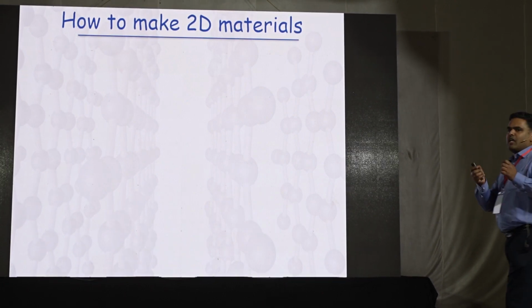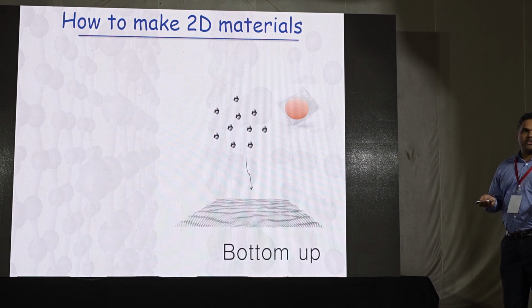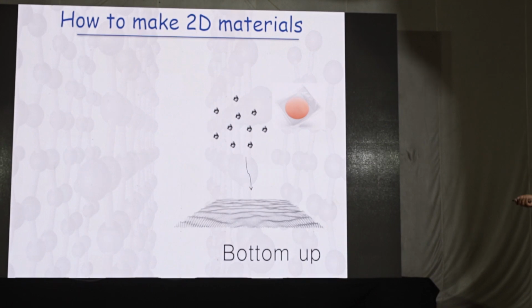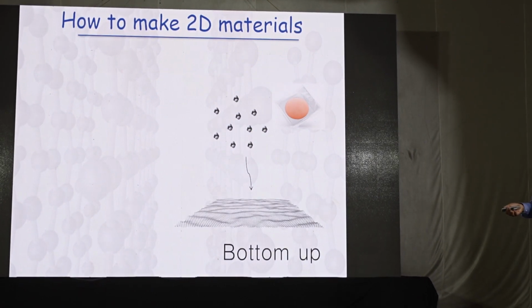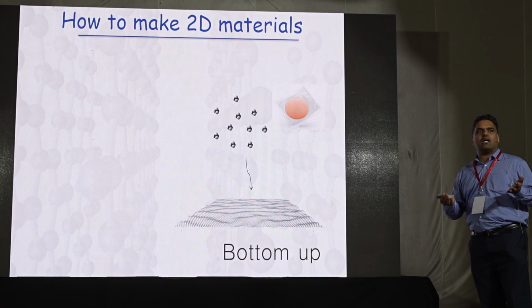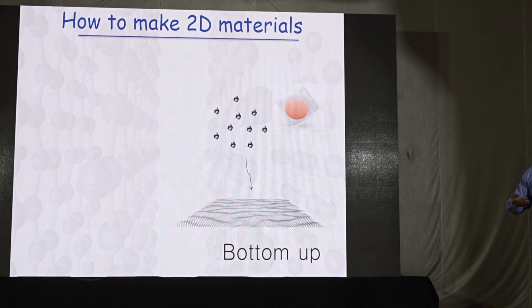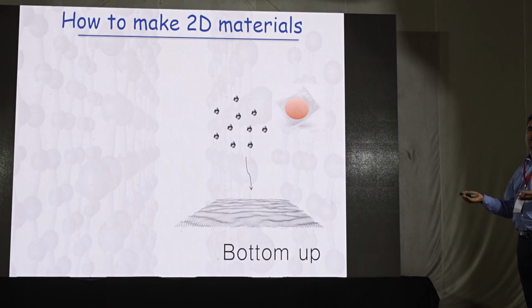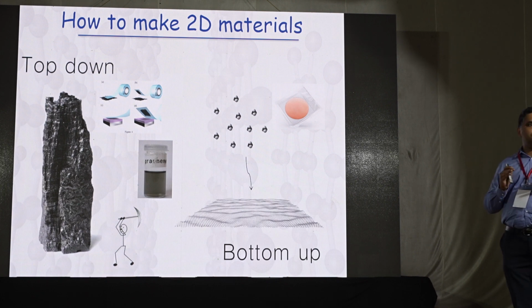Now all of this material actually is very simple to make. You can make it yourself. If I get a piece of pencil and a piece of sellotape, we call it a sticky tape or sellotape, we can make graphene now. If I have a microscope also, I can show you what is single layer graphene. So there are different approaches now. Historically, it's only sellotape, but now, bottom-up approach, what we do is we take individual molecules, like gas molecules, for example, hydrocarbon gas, heat it up at certain high temperature using a catalytic substrate. So then you precipitate that carbon atom or whatever atom you want onto the different surface, so that you get a single layer of atoms. This kind of growth is a self-limiting process, and you can get one atom thick material onto different surfaces.